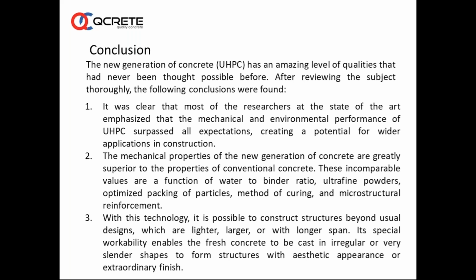in myriad ways. The mechanical properties of the new generation of concrete are greatly superior to the properties of conventional concrete. These incomparable values are a function of water to binder ratio, ultrafine powders, optimized packing of particles, method of curing, and microstructural reinforcement. With this technology, it is possible to construct structures beyond usual designs, which are lighter, larger, with longer span. Its special workability enables the fresh concrete to be cast in irregular or very slender shapes to form structures with aesthetic appearance or extraordinary finish.